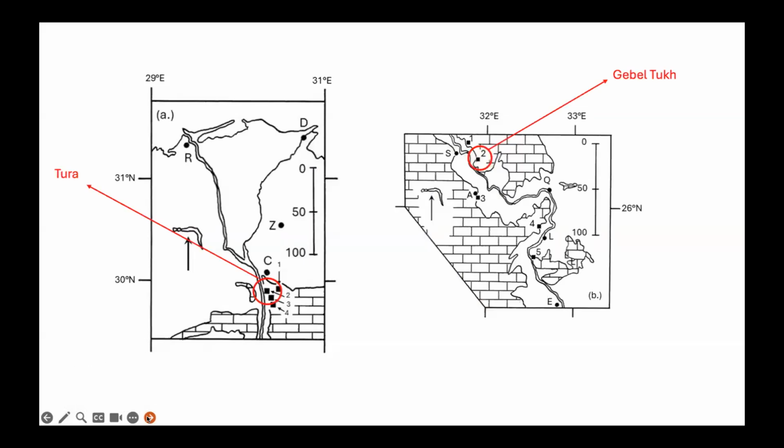Now, based on the work undertaken by Damien and Trevor, the source of limestone for this stela is most probably from the Gebel Tukh quarries in Upper Egypt, so just north of Abydos. Limestone sourced from Gebel Tukh in the south is considered comparable to limestone sourced from the Tura Masara area near Cairo, modern-day Cairo, given their fine-grained and uniform appearance. They are also said to be one of the better quality limestones available to the ancient Egyptians. For our experiment, we thus also sourced some blocks of Tura limestone from Cairo, and I just want to thank Eve Murta, who kindly assisted with bringing these to Sydney for us last year.